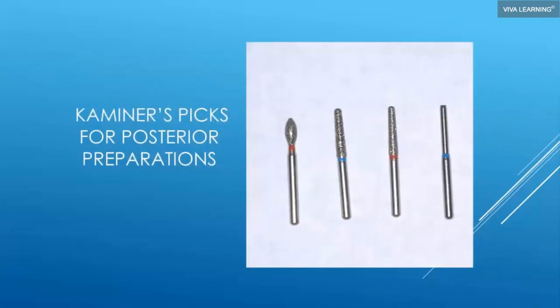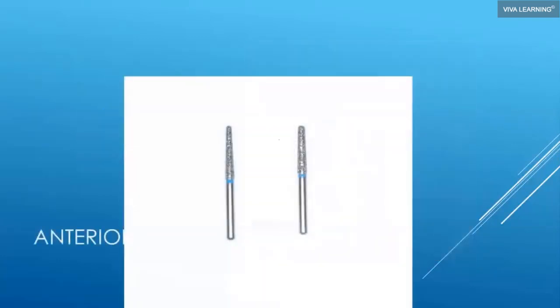These are the burs I use from Microcopy. If you call Microcopy and tell them you heard Kaminer speak, they'll send you a free bur pack. So these are the burs that I use. I use a football diamond. I use an 016 chamfer in a medium grit, an 016 chamfer in a fine grit to smooth it off. And then I have this cute little bur that has only diamonds right here on the edge, and that will allow me to finish my finish line to create an equigingival finish line whenever possible that's nice and smooth. Notice there's no diamonds here on the shank, only diamonds here at the end.